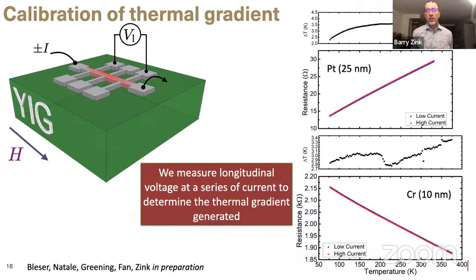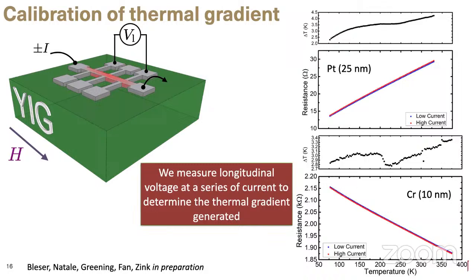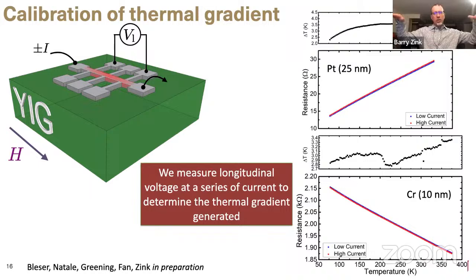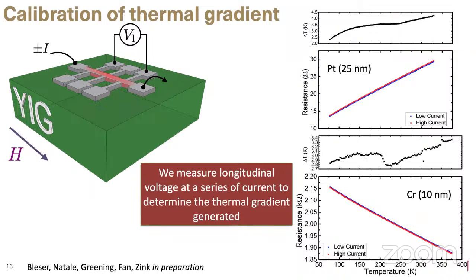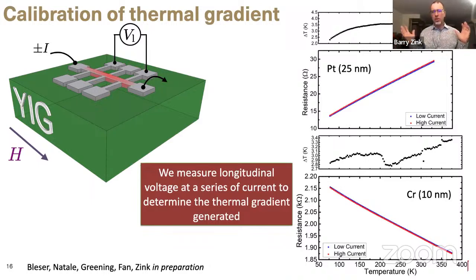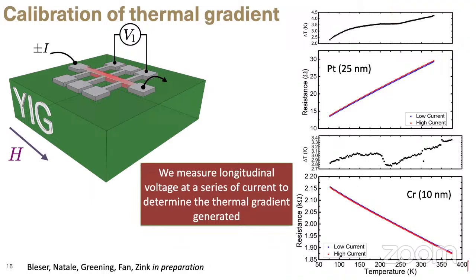Right. Keep in mind what we're trying to do is only locally generate the thermal gradient. We're not like the typical spin-Seebeck setup, where everything is utterly planar, large, the film covers the entire substrate, and it's very important to have a uniform thermal gradient everywhere. Here in this experiment, you don't have a uniform thermal gradient everywhere. If I put a separate thermometer onto the YIG, and in fact we usually produce many Hall bars on a given YIG substrate, have we actually checked it? I'm not sure. But what I would expect and hope is that at any other place distant from the actual Hall bar that we're heating, we would be measuring the same equilibrium temperature that we would have at the bottom of the substrate, right?